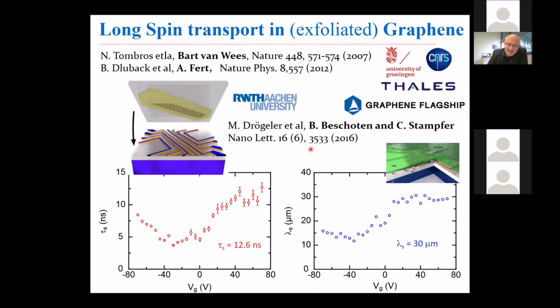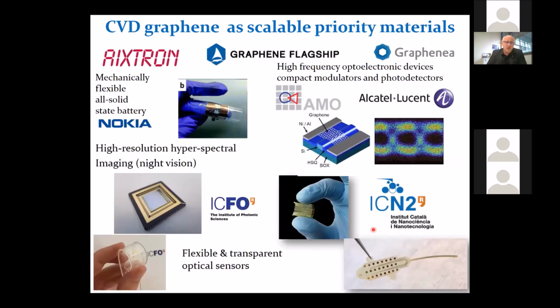So the consortium has demonstrated, using high-quality exfoliated graphene and different types of optimization at the level of single device fabrication, somehow the upper limit of the spin diffusion lengths. Here we have some of our partners' publications where they reported spin diffusion lengths up to 30 micron at room temperature. But the point is that in order to move to technology and application, we had to really focus on scalable graphene and scalable two-dimensional materials.